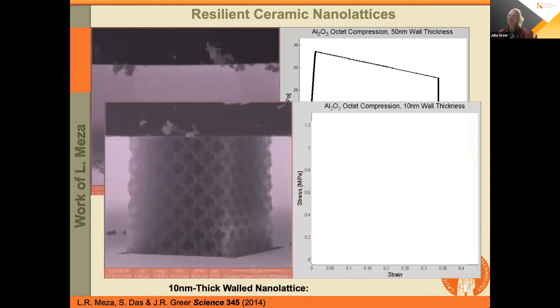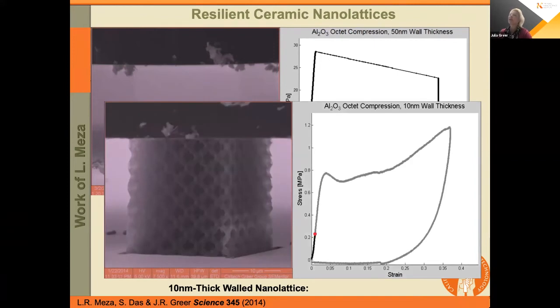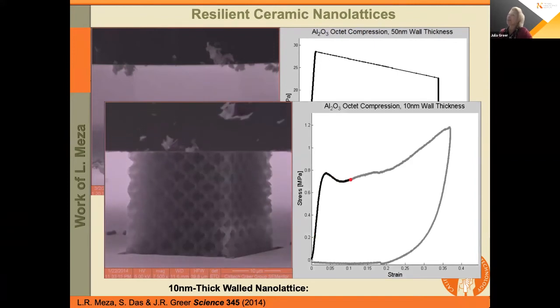Now, if we repeat this experiment, and the only thing that we do differently now is we reduce the wall thickness by a factor of 5, now it's only 10 nanometers thick, same alumina, same brittle material, same architecture, and same microstructure. We would expect it to crush and die even more readily. But what we're observing instead is something very, very different.